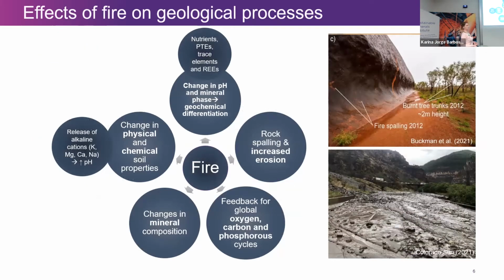So fire has a number of different effects on geological processes that we already know about. So number one, there's a lot of geomorphological effects. So it can cause things like rock spalling, and this is a really nice paper that came out last year that actually found that fires seem to be quite significant in shaping Uluru. So this is the base of Uluru, and there's a flared slope at the bottom, and this research actually found that severe fires were causing charring and spalling at the base and causing this sort of flared slope pattern, which is kind of interesting. Increased erosion is also a really big issue following fires, and that happens because you're destabilizing the soil profile and changing the physical properties of the soil. So if there's a large rainfall event, that can be quite significant.